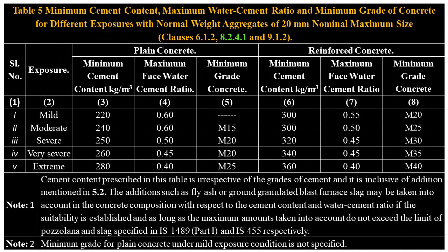In the preceding slide, I introduced 2 tables, Table 5 and Table 6. Let's focus on Table 5. This table provides insights into the appropriate values for minimum cement content and the maximum free water-cement ratio across various exposure conditions. The title of Table 5 is Minimum Cement Content, Maximum Water-Cement Ratio, and Minimum Grade of Concrete for different exposures with normal weight aggregates of 20 mm nominal maximum size,